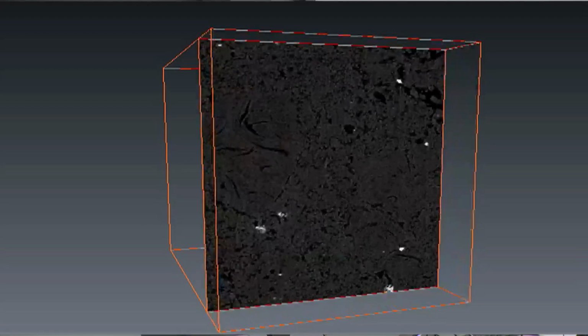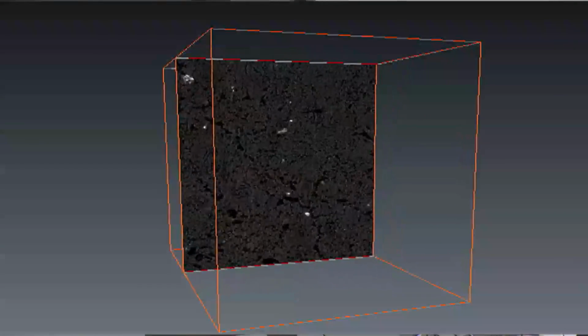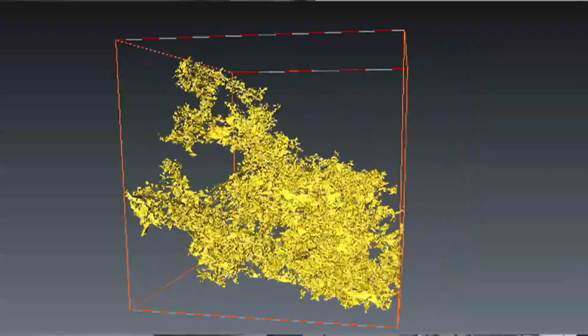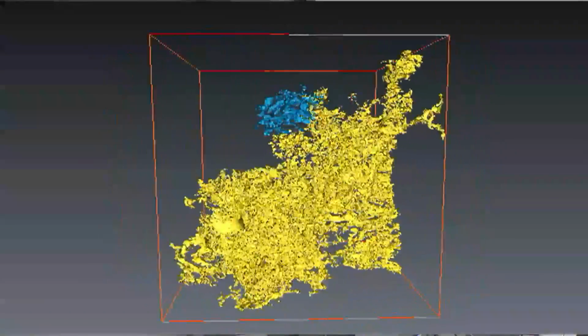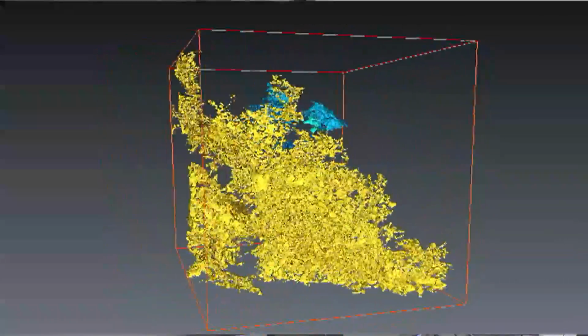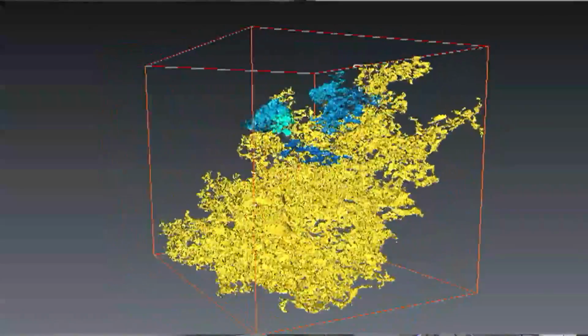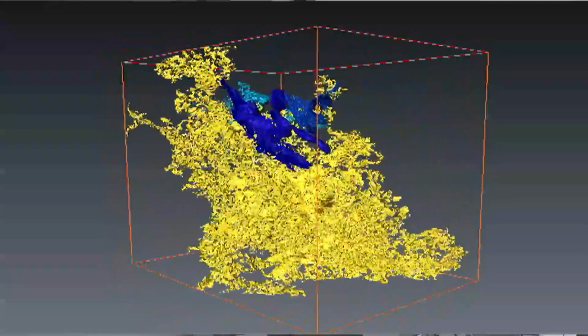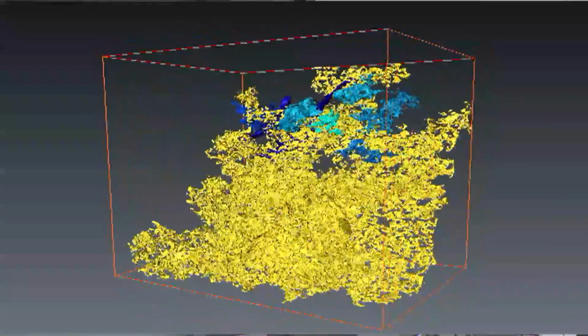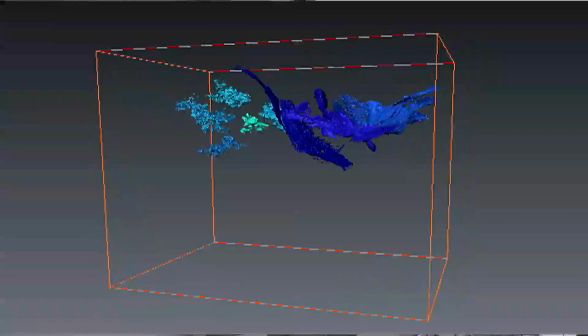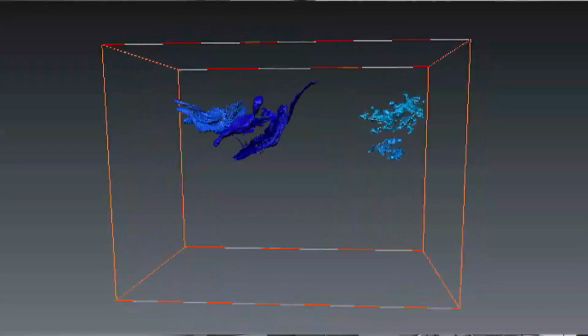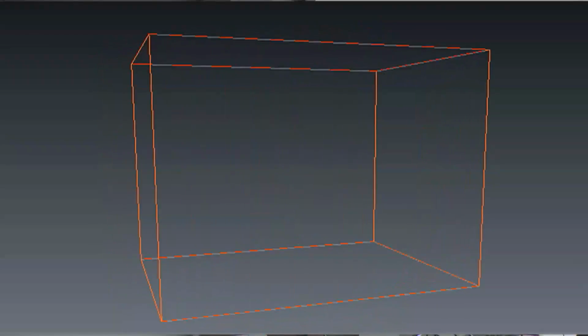So what we do now is we don't just look at the graphite in 2 dimensions, we actually look at the graphite in 3 dimensions using something called X-ray tomography. It's just like a CT scan, but on materials. And this is some results of some work we've done here at Manchester. So you can see here all of the porosity in 3 dimensions within a little block of graphite. You can see some of the cracks that I showed you earlier. All of this porosity is connected to each other, but you can see some other porosity out here which is not connected. That's actually quite important when we come to contamination of graphite. So we can build up a very complicated picture of the graphite in 3 dimensions now.